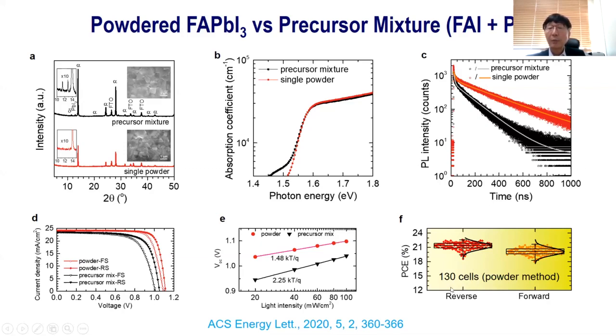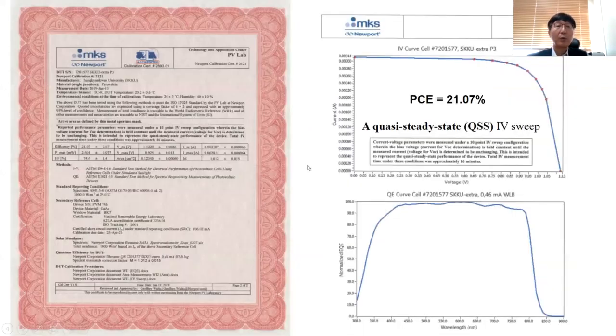However, we made 130 cells, and the statistical data shows very reproducible power conversion efficiency. And with this powdered perovskite material, we certified 21% efficiency, which is consistent with the data we measured in our lab.